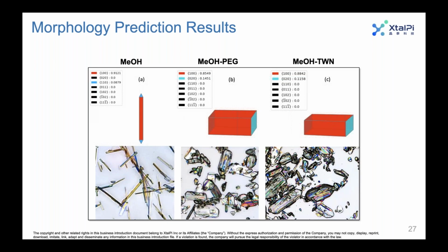We have the opposite effect for the 0 to 0 phase. So it's not seen in the pure solvent. So it's a virtual phase, right? It could exist, but it's not accessed in that solvent system. But when you add the polymers, they change the growth rates enough for this phase that you see that 0 to 0 phase appear in the morphology. So you have a virtual to real transition.